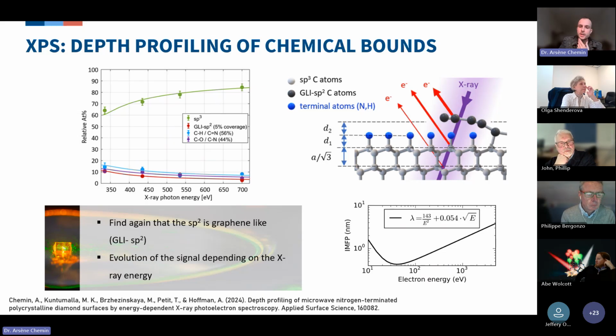And what is nice with that is that you can actually fit this evolution. So if you consider the inelastic mean free path of the electron escaping from the surface, depending on the kinetic energy of the electron, and you make a small model out of it, you can actually adjust this model on the measurements you have. So for instance, here you can see that we measured more and more sp3 component as we increased the excitation energy and less of the surface. And we did that with many different hypotheses on what the surface looks like. And the only convincing adjustment was actually a surface that would look like this.